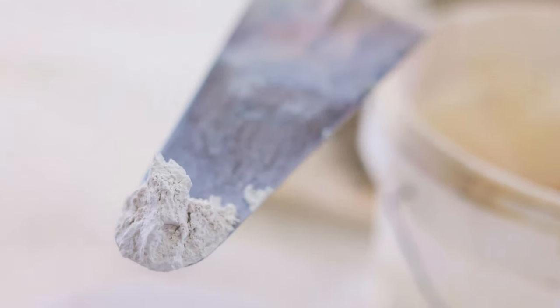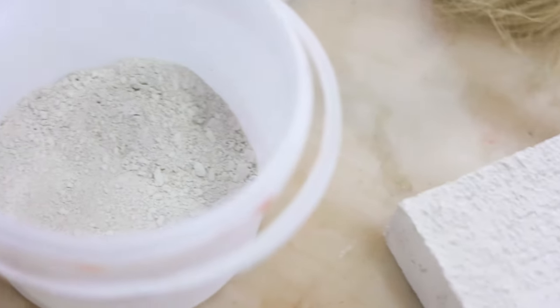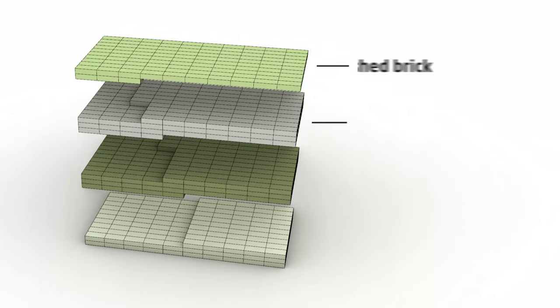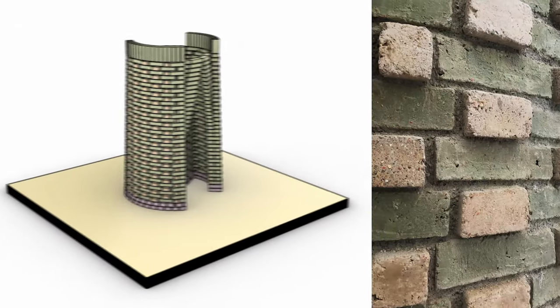The binders were a blend of lime, which is higher carbon, and canal silt, which is zero carbon. All the different colours came from those stock ingredients. Within the two chosen brick types, we had a brownish or warm off-white colour and a slightly cooler green colour. The green was a harder brick containing more lime, while the brownish one had more canal silt, was softer, and had different properties.